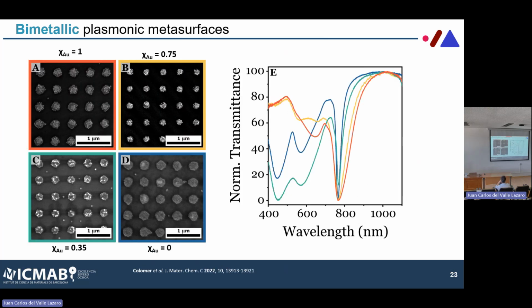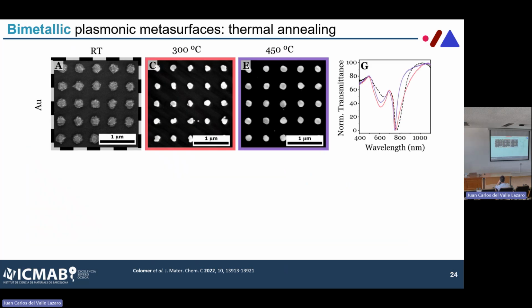So we did exactly the same procedure. We dried these under a stamp, and this is what we got, and we can see the effect. The more silver we have in the system, the better the response. This is expected because silver has better plasmonic properties compared to gold. But what we were interested in was what happens if we heat up the system.